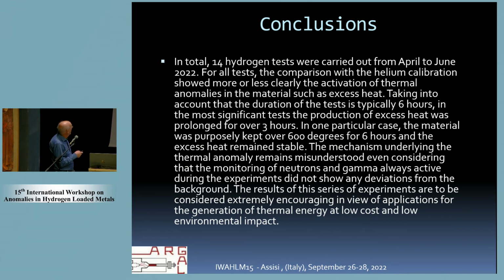In conclusion, in total, I performed 14 hydrogen tests from April to June 2022. For all tests, the comparison with the helium calibration showed more or less clearly the activation of thermal anomalies in the material, such as excess heat. Taking into account that the duration of this test is typically 6 hours, in the most significant tests, the production of excess heat was prolonged for over 3 hours. It means that in the middle of the test, we began to have extra heat.